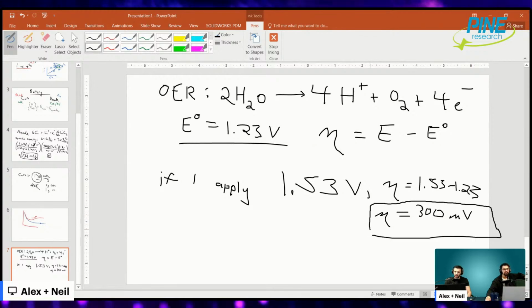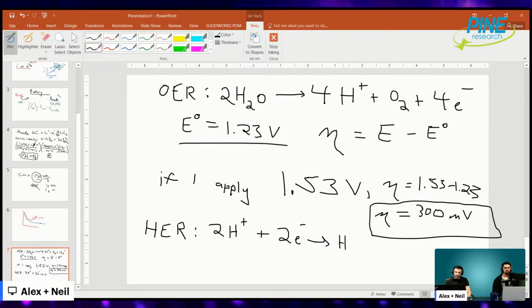Okay, so that's my overpotential. So what that's saying is that I have applied 300 millivolts of potential above the standard thermodynamic potential for which OER occurs, basically. And so it's like a driving force. In the absence of other things, of course, like diffusion and other stuff that we know, you have a higher overpotential, you're driving the reaction more and more, basically. And so without doing more craziness, the hydrogen evolution reaction is a similar thing. It's actually much easier. Watch me screw it up. We have two protons plus 2 electrons gives me hydrogen gas. And this one's a reduction, doesn't really matter either way. The E0 is by definition 0 volts. So this is like the reference reaction for electrochemistry.